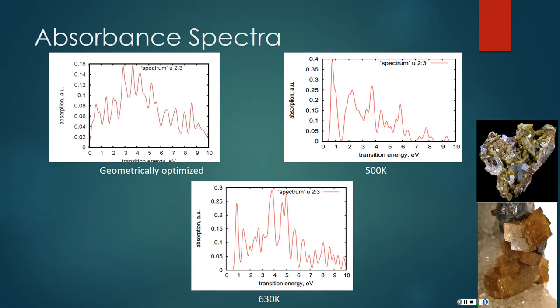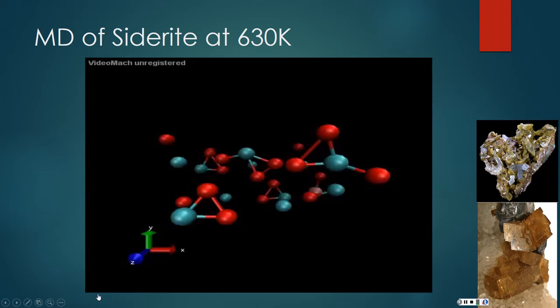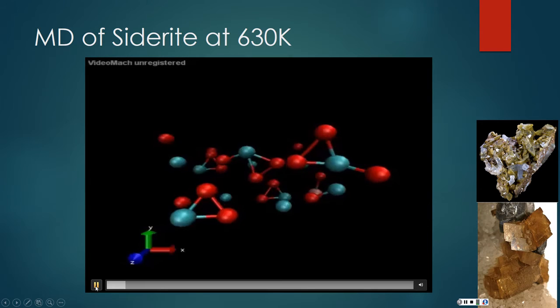But for this absorbance spectra, we can assume that here the iron is in the high spin, or it may be possible that the crystal field splitting is very far from the ideal or high symmetry. Here the iron d orbitals are offset from each other instead of forming a region. And we can also see that the iron orbitals are hybridized with the host orbitals. This is the MD of siderite at 630 Kelvin.